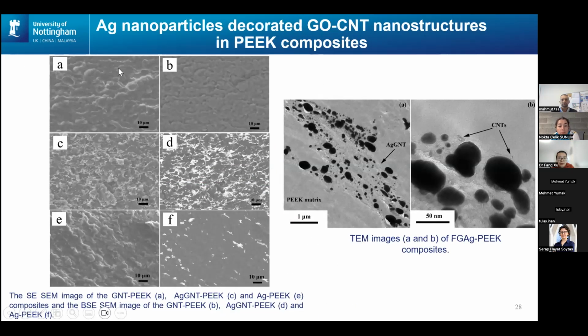These are the microscope images. On the left are the SEM secondary electron images. Because silver is quite heavy, we use backscattered images to look at the silver particles, shown on the right column of the SEM. We can see they are very bright and quite uniformly dispersed at relatively lower magnification. TEM images confirm the existence of silver particles and graphene nanotube structures. This is the PEEK matrix, with silver and GNT here, and we observe carbon nanotubes as well — this is a cross section of a carbon nanotube.